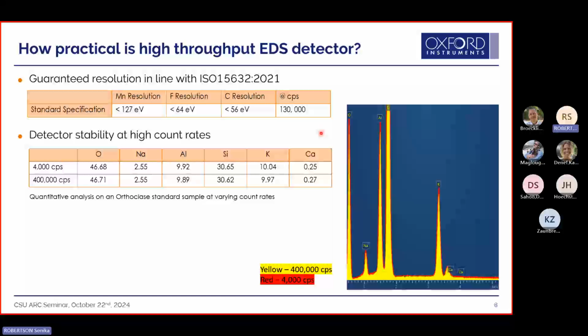The point with the newer technology is the max resolution, which is the peak shape. So full width half maxima is guaranteed up to 130,000 counts per second. You can go up to 200. In fact, the data here is showing you between 4,000 and 400,000. The peak shape is not spreading too much. It's more that at higher count rates you end up having more sum peaks and other artifacts. So when you're doing the most precise analyses, you'd want to be around 130 to 200,000.